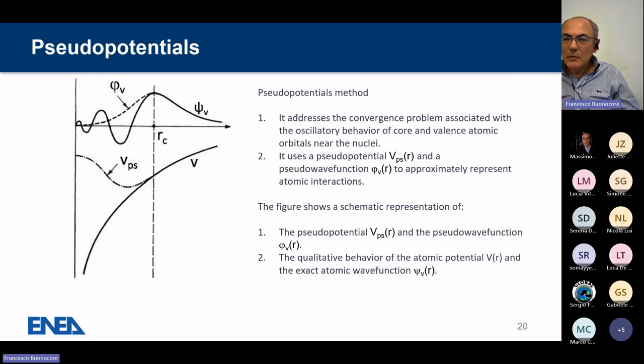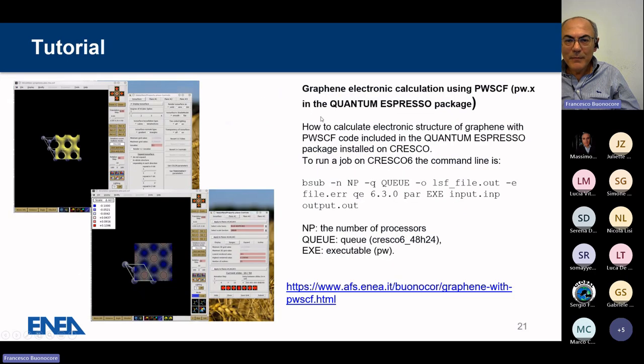And this is not a bad approximation. It's a very good description of your system. It solves probably a numerical problem of density functional theory, because when you solve this problem with your computer, these oscillations are a problem. That issue is addressed by adopting the pseudo potentials.